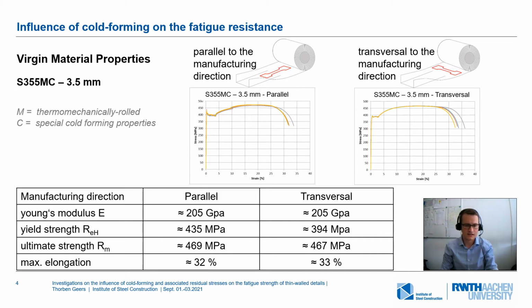We have tested this typically used material for high storage racking systems in the two main directions, so parallel to the manufacturing direction and transversal to this direction. And you can see in the stress strain curves that there is no big difference in the values of the properties. So we have the same Young's modulus in both directions of 205 gigapascal. We have nearly the same ultimate strength of 469 and 467 megapascal, and we have a maximum elongation of 32 or 33%.